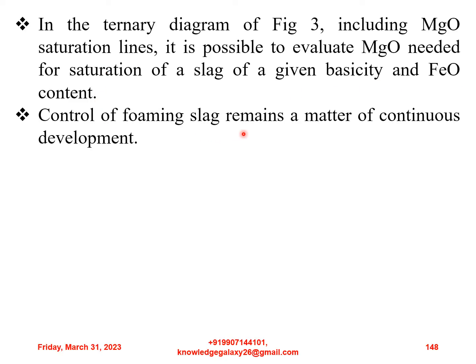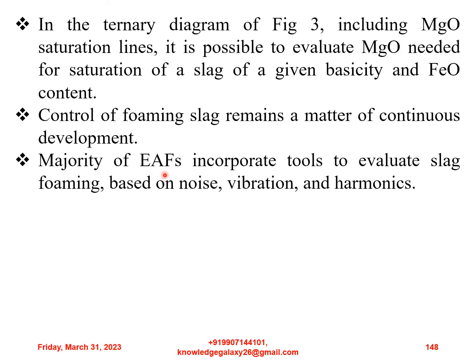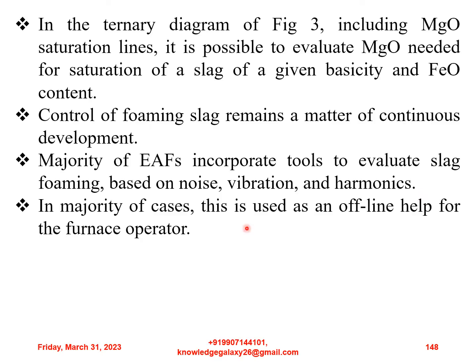Control of foaming slag remains a matter of continuous development. The majority of the electric arc furnaces incorporate tools to evaluate slag foaming based on noise, vibration and harmonics. In the majority of cases, this is used as an offline help for the furnace operator. But some electric arc furnaces have recently introduced online control of the carbon and oxygen injection for slag foaming based on the mentioned measurements.